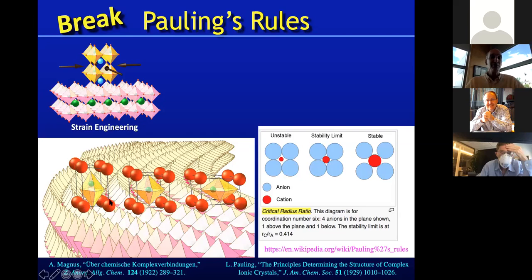Or it could be that you have a substrate, and this is again a perovskite substrate, that is a little bit smaller than the equilibrium spacing of the atoms that you're raining down on top of it. But to save the energy that it would cost at that interface by forming defects, as long as the film is thin and the strain is not too much, those atoms might like to follow the existing template of the underlying substrate and form with compression, biaxial compression, to follow the shorter distance of the substrate. So that's what I've tried to indicate here in this cartoon.